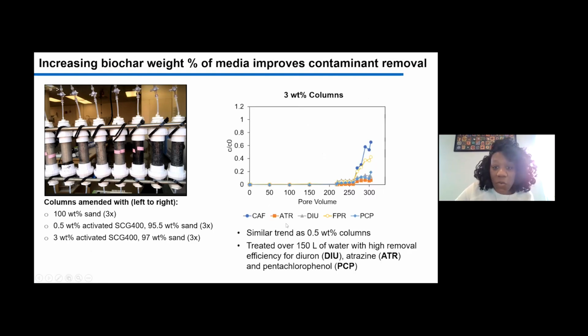And what we see is, for the bulk of the representative trace organic contaminants in the stormwater runoff, we have tons of removal here. So 100% removal up until about 220 or so pore volumes, where we start to see some breakthrough of the contaminants in the column effluent. And depending on the chemical properties of the trace organic contaminant and their interactions with the biochar, we see varying degrees of removal here. So this is a great preliminary case study to say that this material does work and can work for infiltration systems. And we're going to expand that analysis for the trace metals and other types of pollutants as well in stormwater.